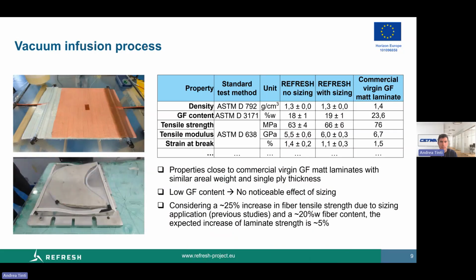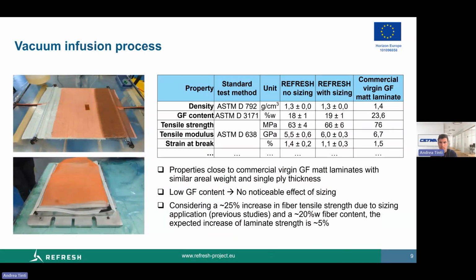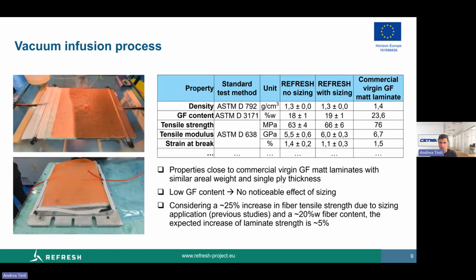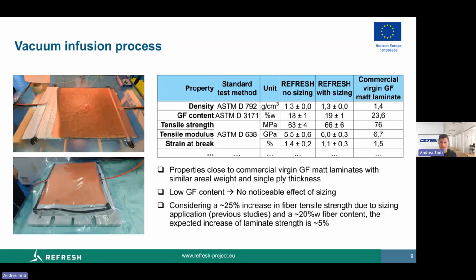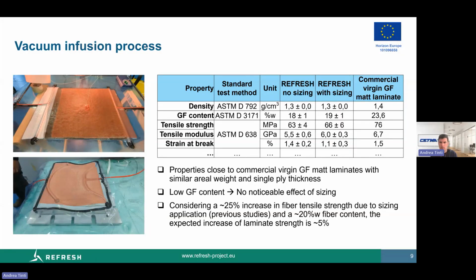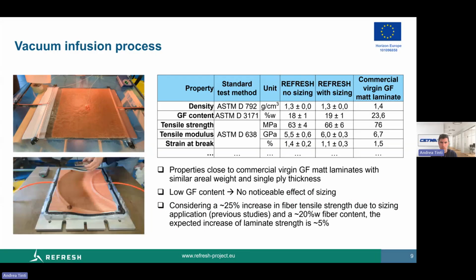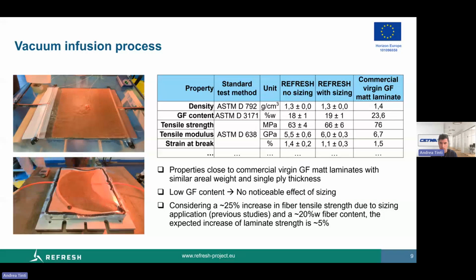Then, with the produced non-woven mat, the vacuum infusion process of both flat laminates and more complex shapes was studied. This is a manufacturing process of great interest in many industry sectors. Mechanical properties measured on infused laminates based on our recycled mat were found to be very close to commercial virgin glass fiber mat laminates with similar features, thus confirming the good residual quality of the used pyrolyzed glass fibers.